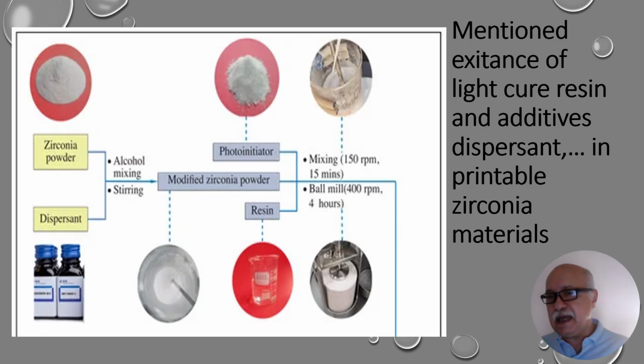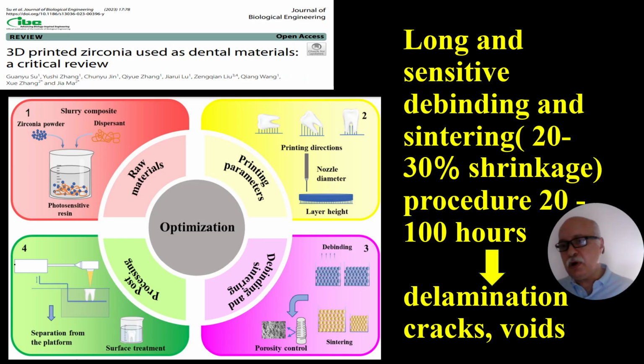As mentioned, the existence of light cure resin, additive, dispersant, and so on is necessary for preparing a stable slurry in printable zirconia material. Both long and sensitive debinding and sintering, which involve 20 to 30% shrinkage, can take from 20 to 100 hours. These problems lead to delamination, cracks, and voids.